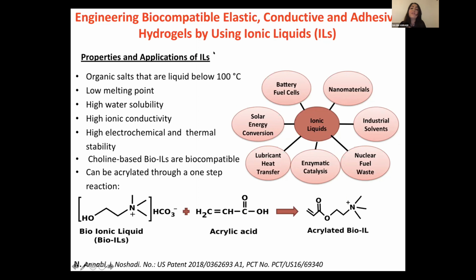So we went through different sources of component that we can use to give conductivity to our naturally derived polymer. And one category of this component is ionic liquid. Ionic liquid are organic salts that are liquid below 100 degrees. They have high water solubility and they have high ionic conductivity. So a specific formulation of bioionic liquid, it's choline-based bioionic liquid, is also known as highly biocompatible.